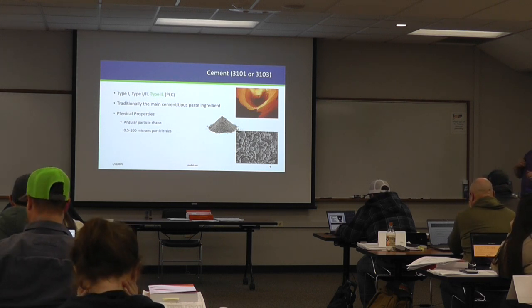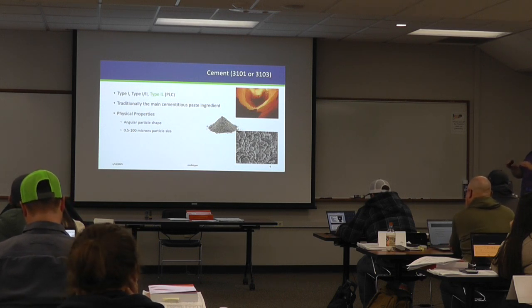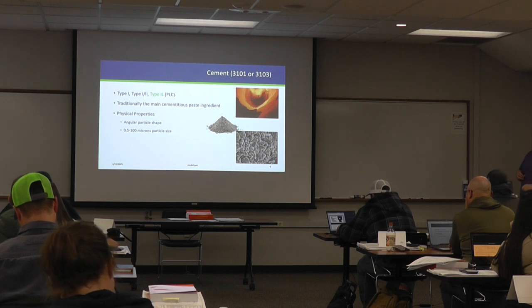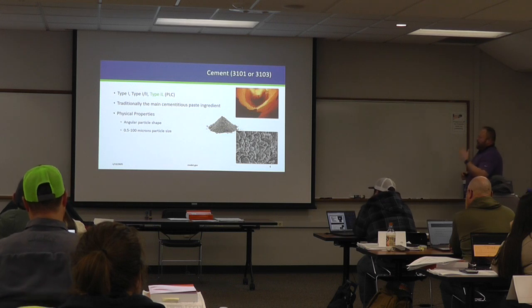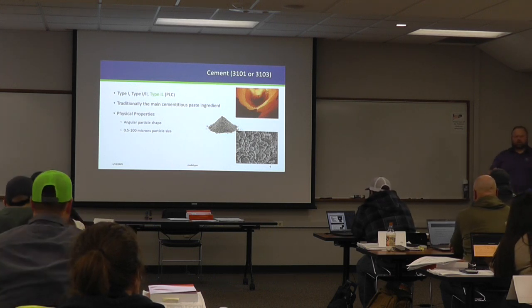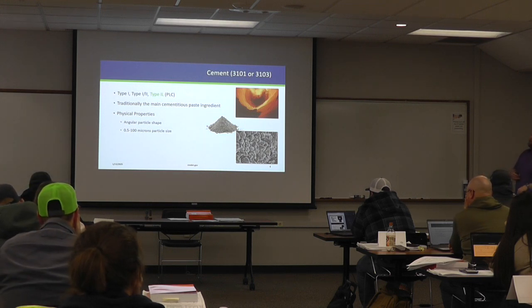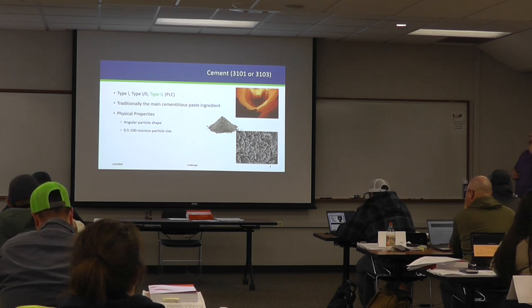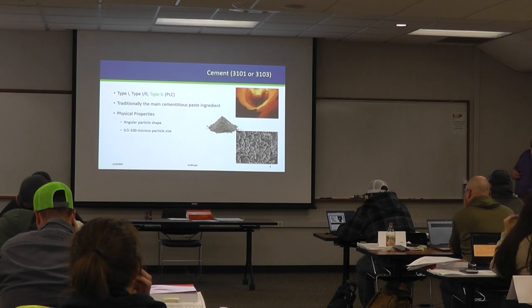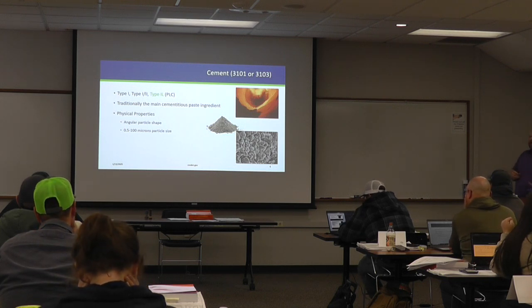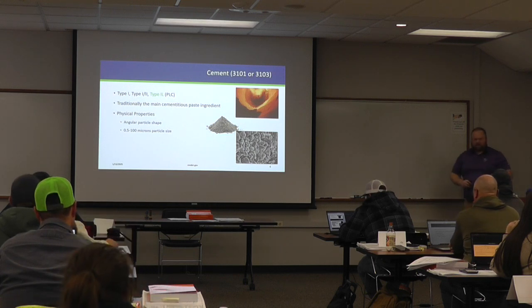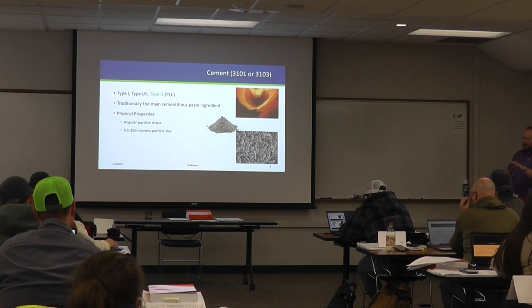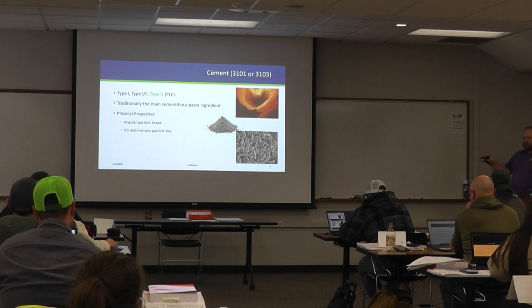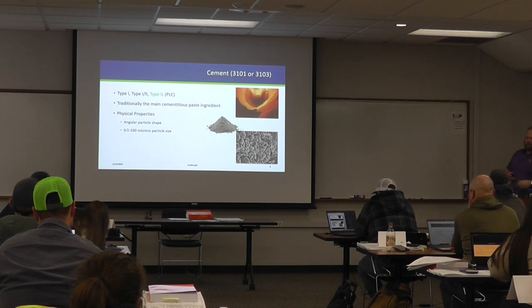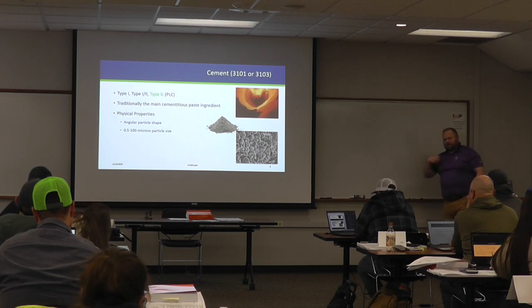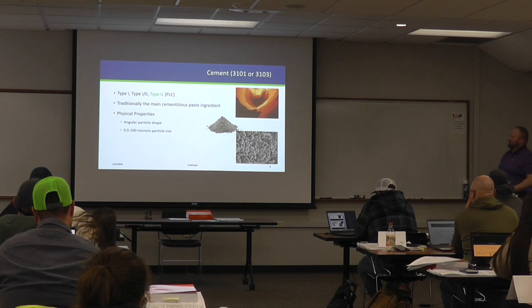Some contractors might say that finishing is a little bit different, so the water demand's a little bit different, but it's not enough to really change materially what happens out on floors using type 1L cement. And that's in response to the global target that the cement industry has on their back with their global warming potential. So in order to make the cement, it releases a lot of CO2. So if they can take 10% of that out of every mix and put in this limestone, which is essentially inert from their carbon release, they're basically gaining 10% on their global warming potential right there. And so it's not just MnDOT that is pushing for that kind of stuff. In general, the cement industry across the globe is looking for ways that they can cut down on the carbon and push it out. So all that is to say, basically every concrete mix that we pour in Minnesota has type 1L cement.